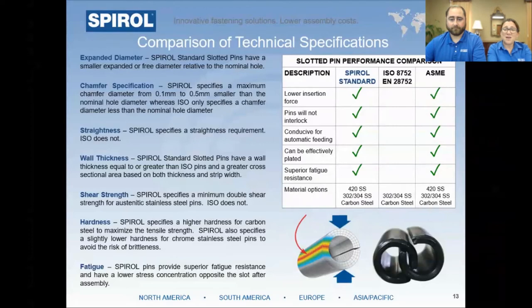As a matter of fact, many issues that customers come to Spirol for are solved simply by replacing an ISO 8752 pin with a Spirol standard or ASME slotted pin. More specifically, if you ever had issues getting a slotted pin started into a hole or that required really high insertion forces, you may well have been using an ISO 8752 slotted pin, which, by the way, Spirol also manufactures. This is because the ISO standard does not specify a specific chamfer diameter, and it also has a larger diameter than these other standards, so it has to flex more in order to get into the hole.